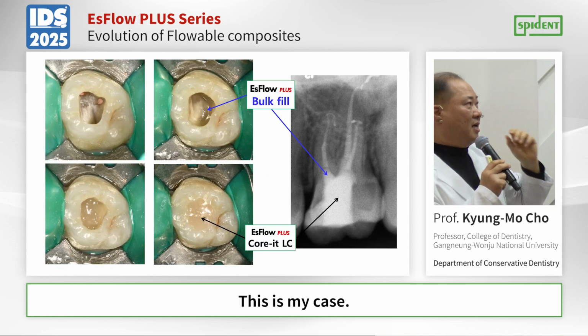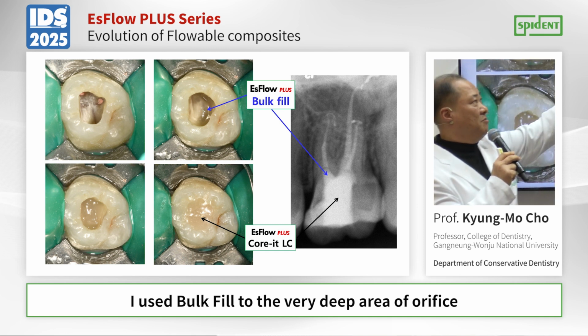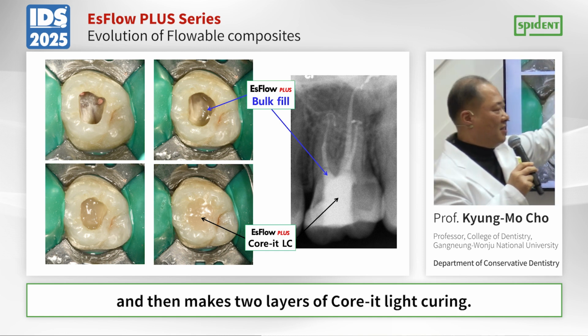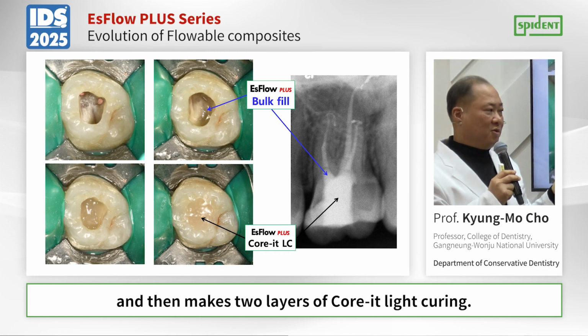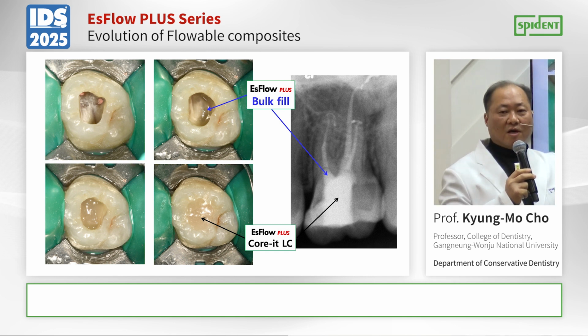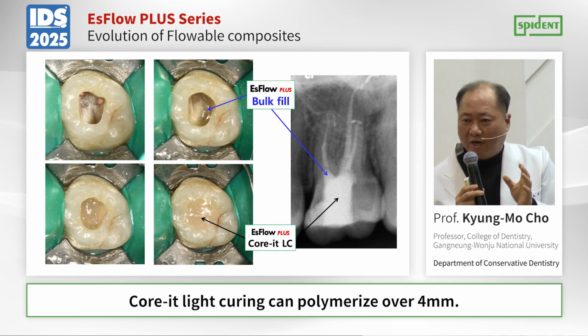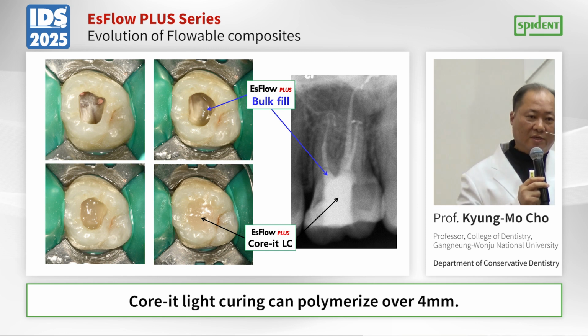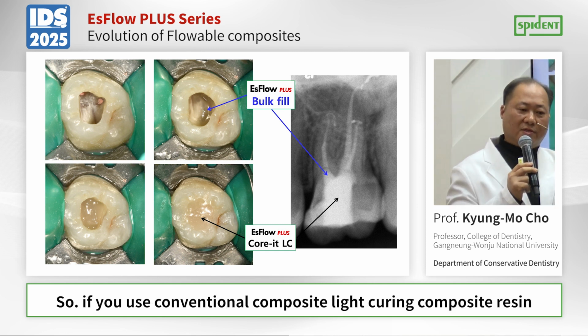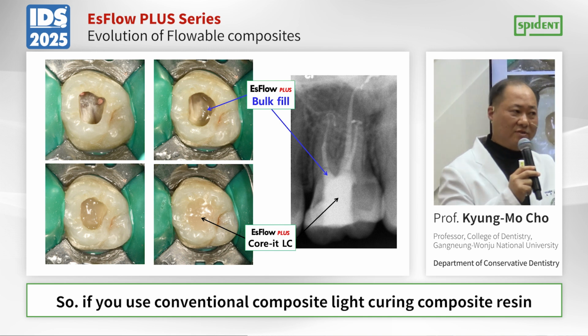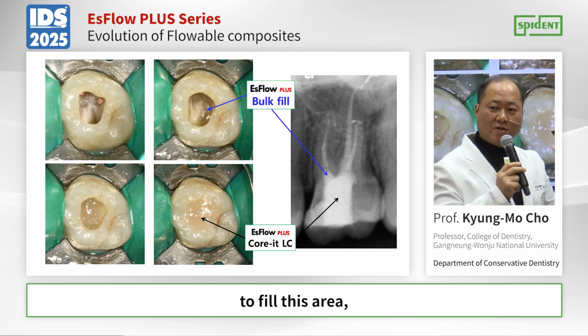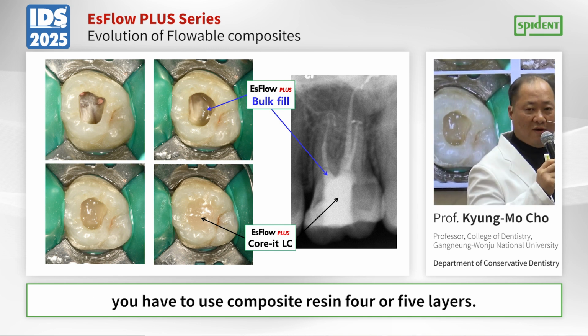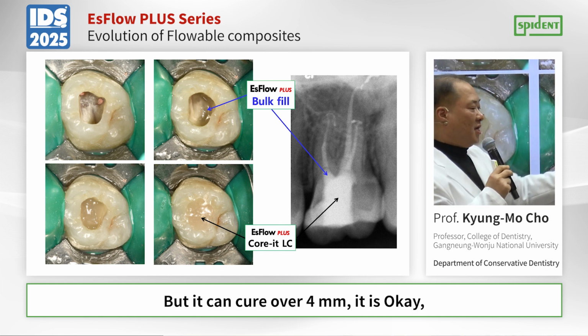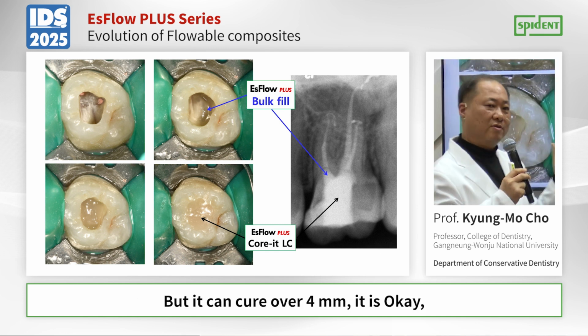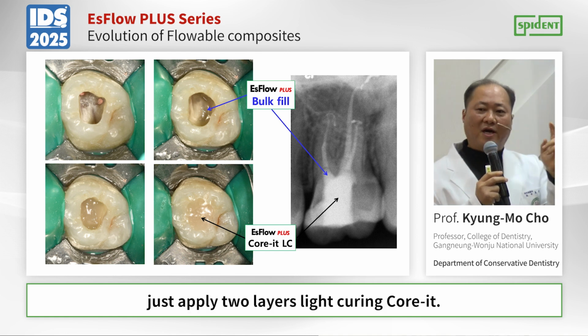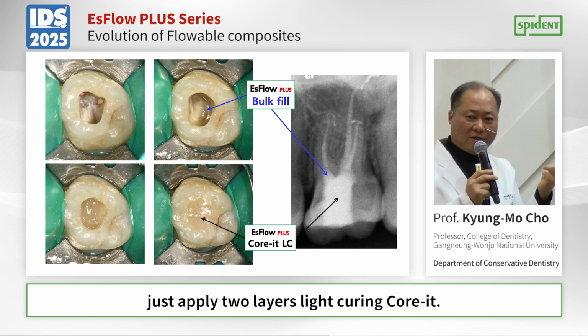This is my case. I used bulk fill in the very deep area of the orifice, and then made 2 layers of core light curing. Core light curing can polymerize over 4 millimeters. So, if you use conventional light curing composite resin to fill this area, you have to use 4 or 5 layers, but this can cure over 4 millimeters. So it is okay just to apply 2 layers of the light curing core.